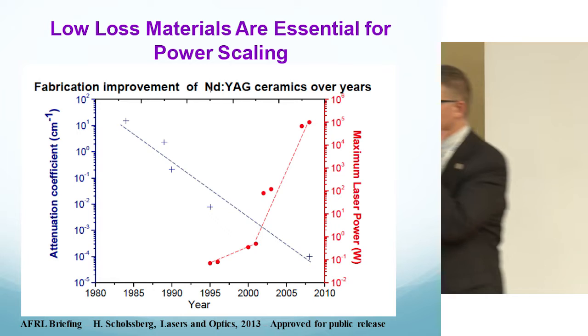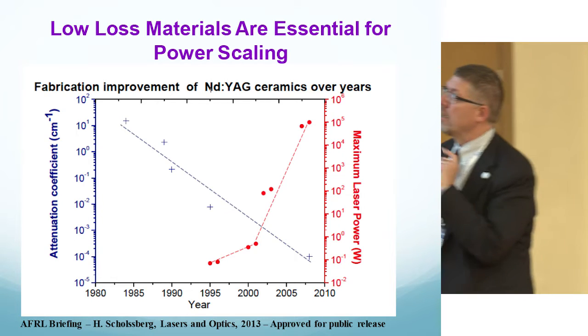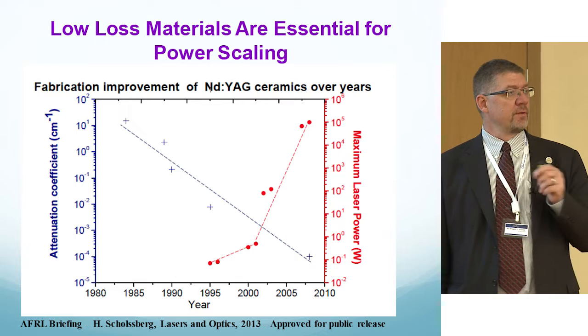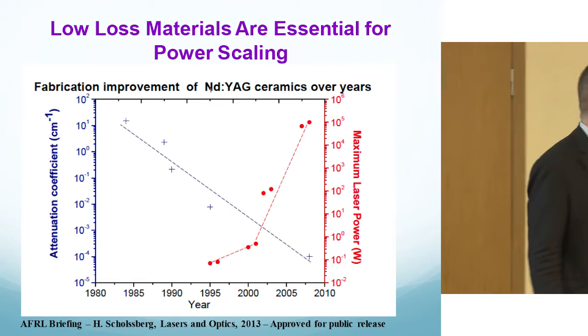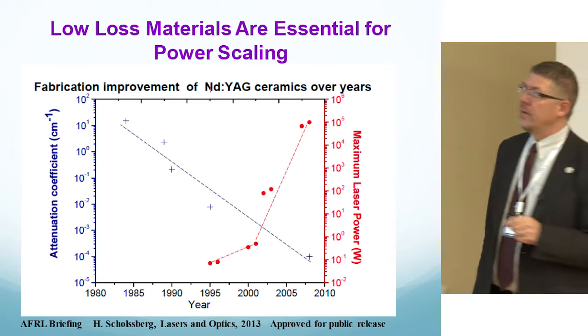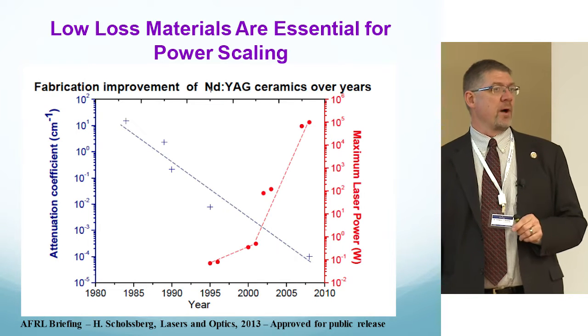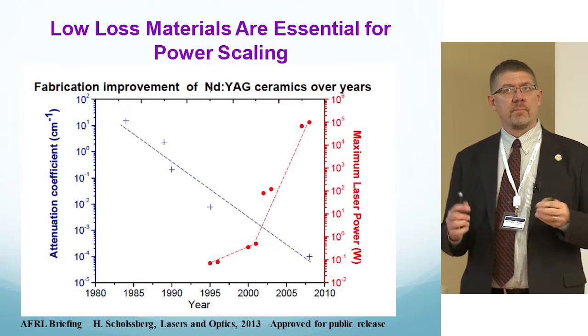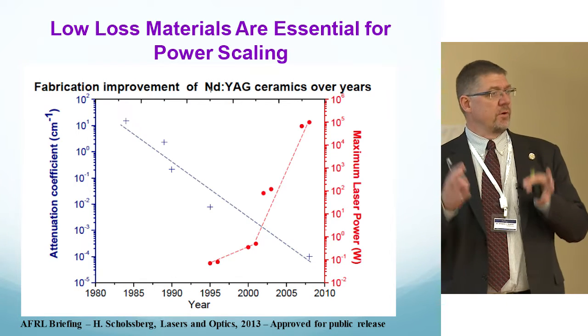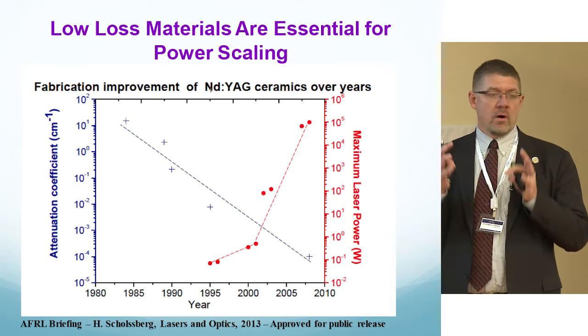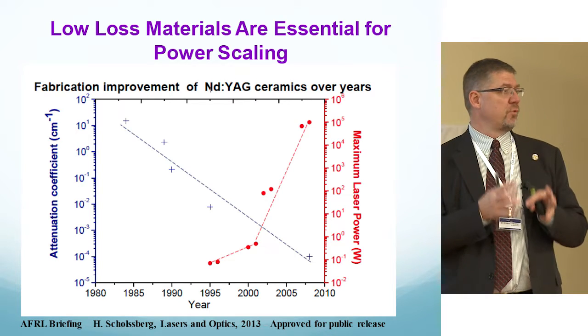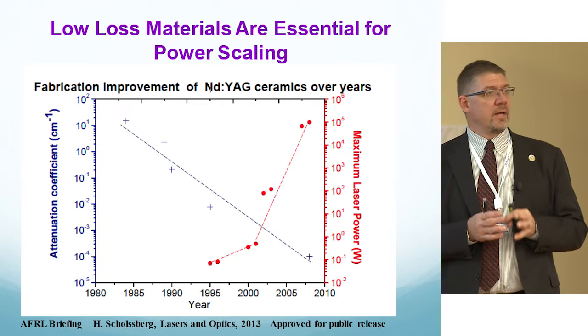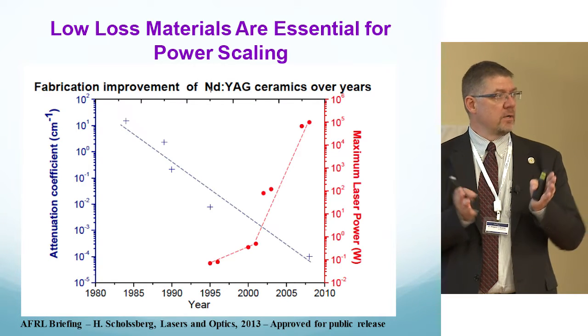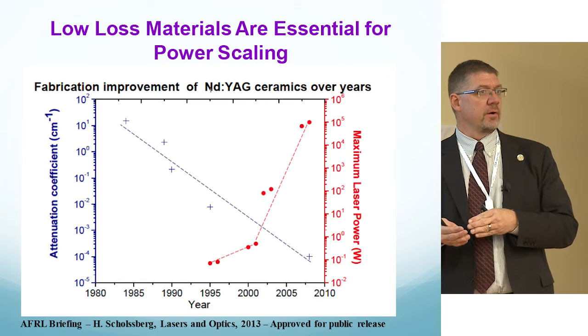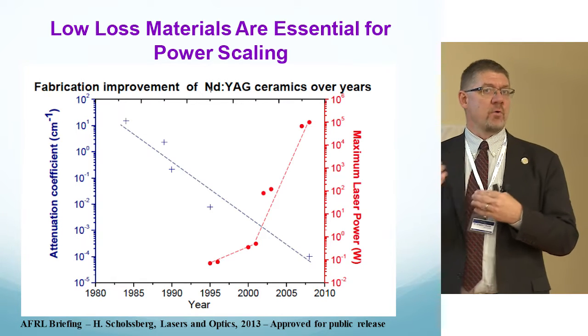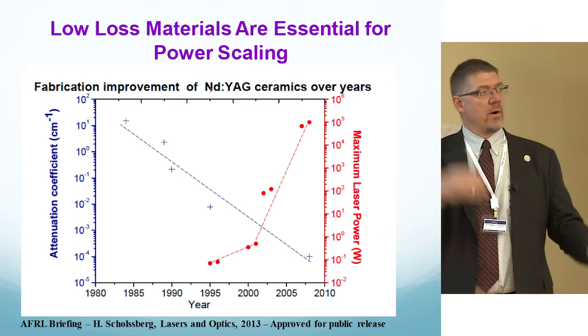But I think this is probably the most important slide to really understand, is that the fabrication improvement of ceramic YAG, that is the amount of loss in the material, really drives the ability to extract output power from the solid state laser. And the reason being is that the larger that you make these crystals, ceramic crystals, and the harder you pump them, if you have absorptive or scattering losses in the material, it's going to cause the beam to either thermally bloom out or thermally focus and damage the bulk gain material. So a good way to map out the quality is to monitor laser output power as a function of losses.